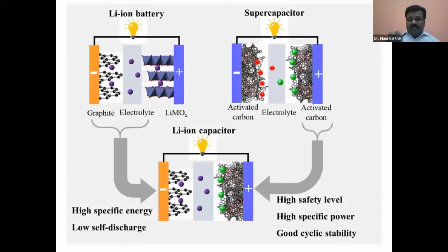Then the supercapacitor gives very little energy density, but because of the very fast adsorption, it delivers very high power. But here the kinetics is controlled, because of the kinetic control, your rate of reaction, the intercalation, is very slow. That's the reason it delivers very low power, but the energy density is very high.